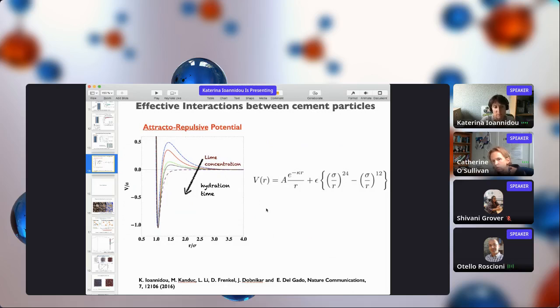Yeah, so is that the only potential governing the formation? Oh, fantastic. Yes. So if you use a different type of simulation, you could do something more complicated. But here, what we wanted to do was really to stay with a simple potential that stays close to atomistic simulations and experimental data that we had. And we were able to do this using a typical symmetric potential. So we didn't need to go for something more fancy, which was good for the simulations because they were at least light from the point of view of the interaction.